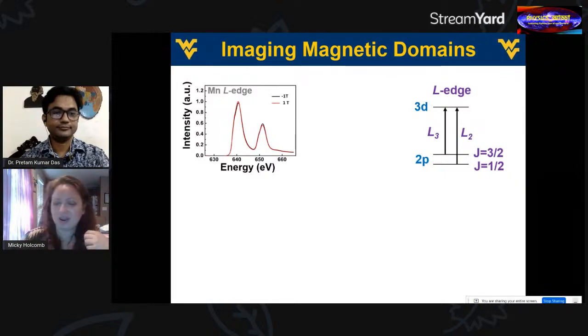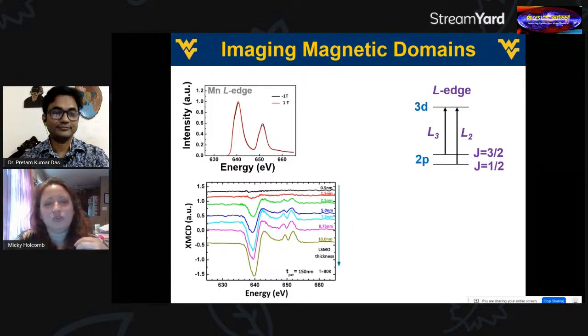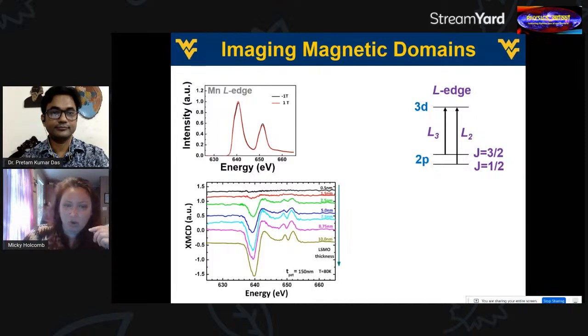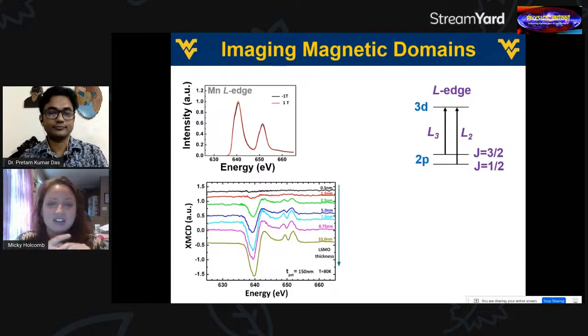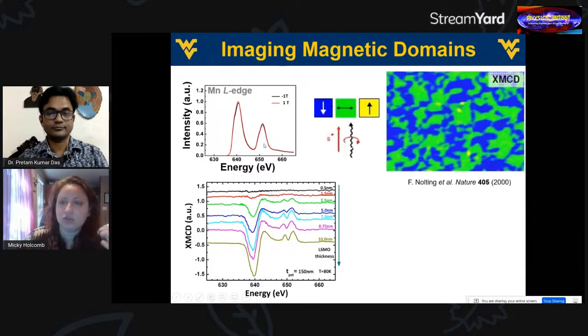That looks really tiny, right? But it turns out that if you do this systematically, you can see that this really tiny difference, so here on the bottom, I'm just taking the subtraction between these two spectra on the top. You can see that here I have a whole range of sample thicknesses, that this is actually a technique that you can do very quantitatively and measure the magnetization in your sample. And then if you sit at one of these places where you have a big difference in the dichroism, you can actually image your magnetic domains.